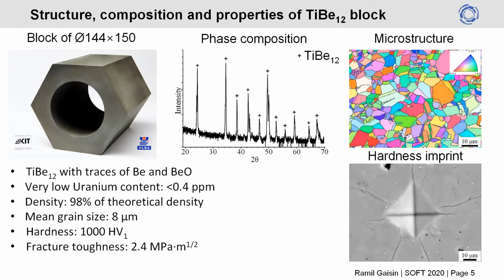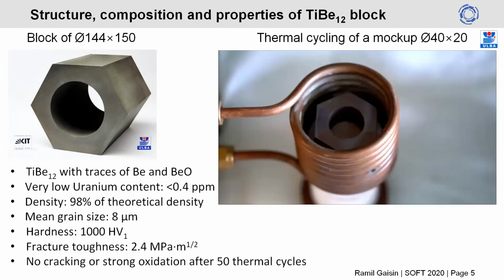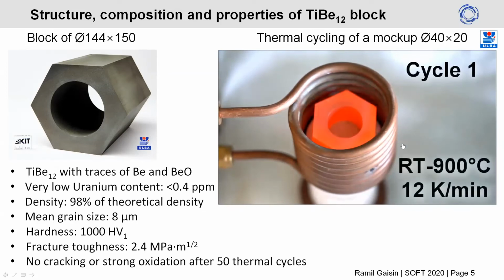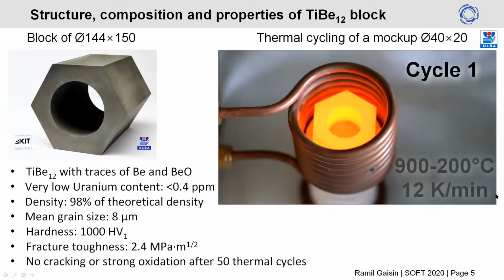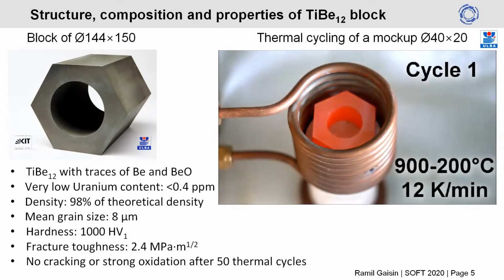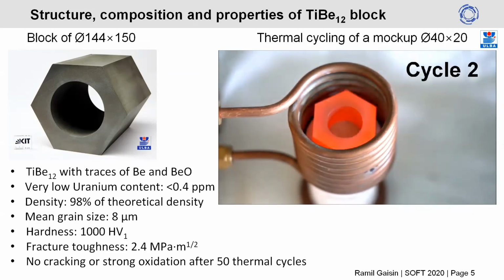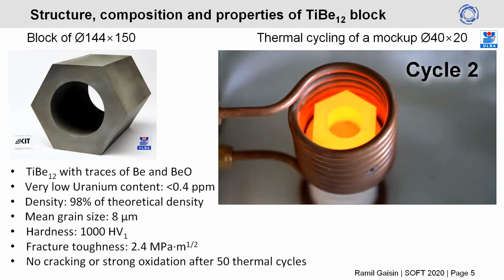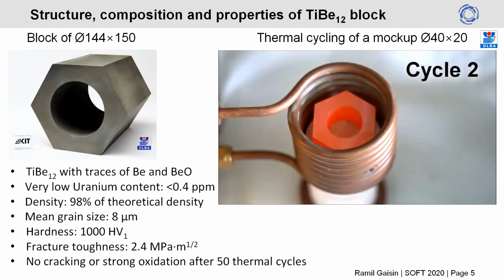And one very important point, during the operation of the fusion reactor, the beryllide block will experience rapid heating and cooling. I will start a video, again courtesy of Ulba, in which we mimic the operating conditions of the DEMO reactor. The beryllide mock-up is placed in an induction furnace. It is rapidly heated up to 900 degrees, the video is accelerated, and then cools down to 200 degrees in a compressed atmosphere. Another cycle, the block shines like the sun and turns gray again.